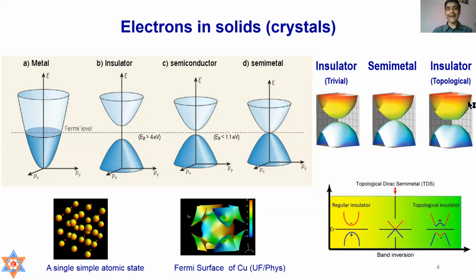So the semi-metal is lying in between the trivial insulator and the topological insulator, wherein due to the inversion of the band, the gap appears again. You see the difference between this trivial insulator, which has a smooth gap, and the topological insulator, which has a different nature of gap. This is because of the band inversion, which I will not discuss much, but I just try to tell you that the semi-metal lies somewhere in between these two. That's why the nature of this semi-metal is very, very important.